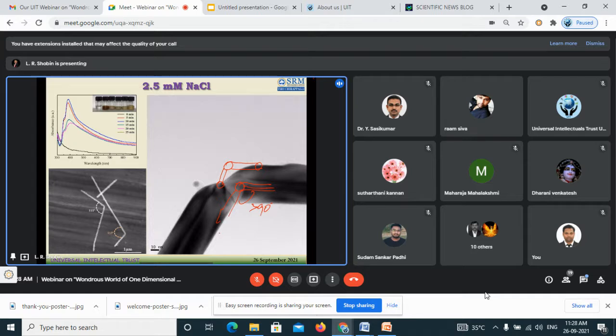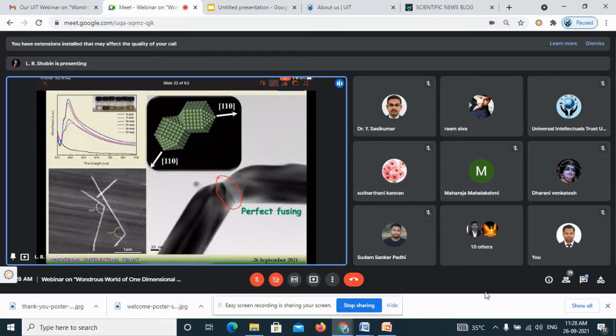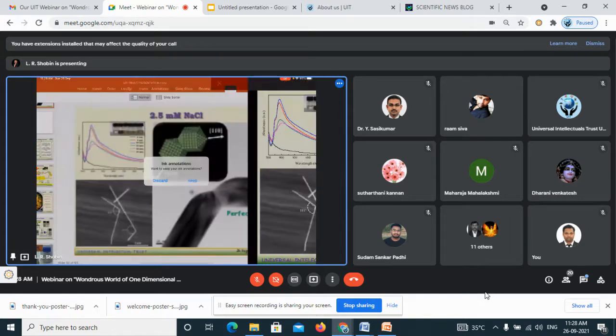If you check this fusion, this is a perfect fusion actually. This fusion is very perfect. It is starting from the growth of one single crystal. So this is a perfect fusing, and we can expect this may be the growth mechanism, because you can see there is a gap over here also. That gap you can see here also, and this angle is a wide angle. Here also the angle is a wide angle. So at this plane, atoms have started hitting, and it is producing the growth. This side was passivated with the PVP. I will probably explain this in the next couple of slides.